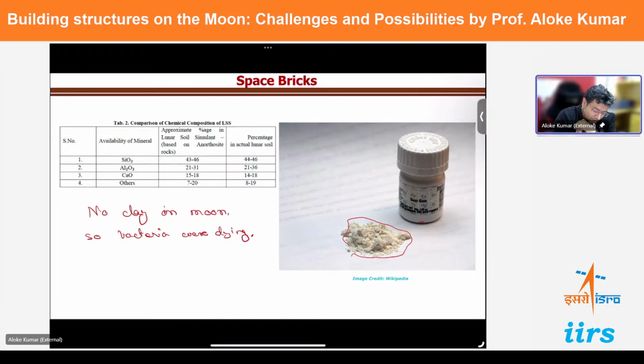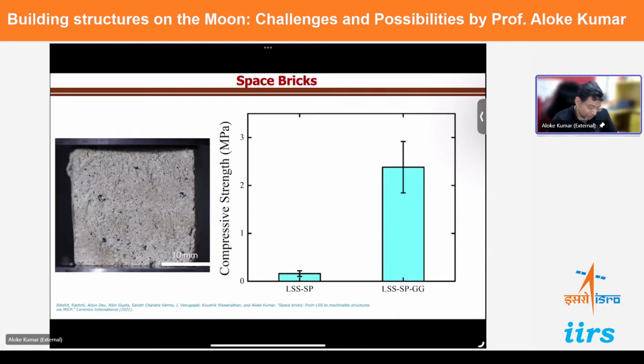But we said, okay, we will put very small amounts, less than 1% of this guar gum into this clay structure. So if you are creating 100 kgs of this slurry, you will put only 1 kg of this guar gum there, or less than that. And when we did that, the bacteria started growing very, very well. And what you got is you got this really, really nice brick-like structures.